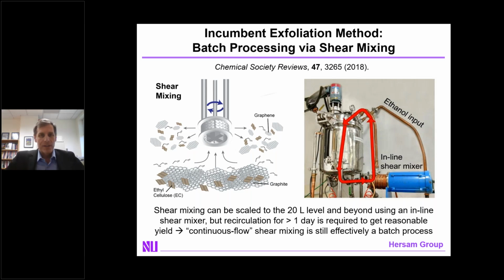The way this is typically done is to take your bulk van der Waals solid, put it into a suitable solvent, often add a surfactant or stabilizing polymer, and then agitate. The most common incumbent method for this agitation is shear mixing. Shear mixing is a method which is quite effective, and in our lab, it's been scaled to the 20-liter level, utilizing inline shear mixing. But the catch is that this process requires recirculation for timescales on the order of a day to get reasonable yield. As a result, while this looks like it's continuous flow, it's still effectively a batch process.